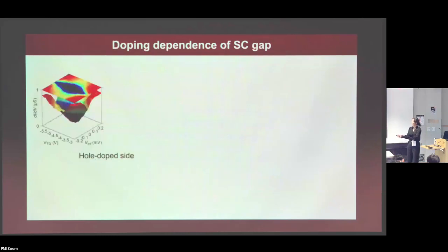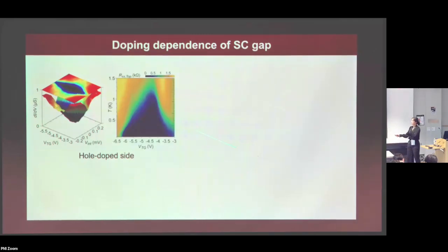Okay. And just one last thing that I want to mention is that we can also look at the doping dependence of the superconducting gap. So here's the tunneling spectra as a function of the top gate voltage. This is across the superconducting dome. And next to it, I want to put a totally different measurement, which is the resistance as a function of temperature and doping. So these are unrelated measurements. One is tunneling spectroscopy. The other one is just the temperature dependence of transport. It's just in the same device.